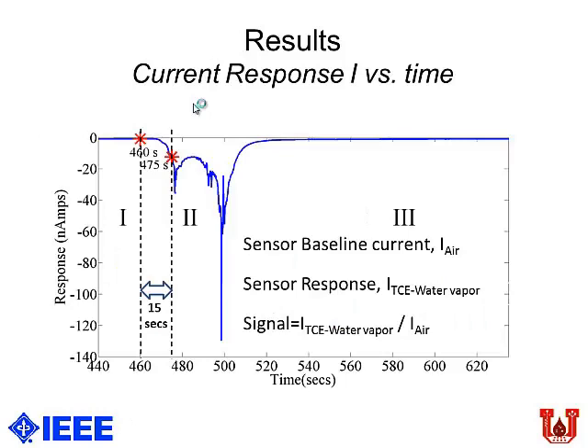So this is the actual sensor response. Your baseline, that's region 1, is when air is passed over the sensor. You don't see much significant current. And at 460 seconds, you cut the air out. Instead, you pass air through your water containing trichloroethylene, and then carry it over to your sensor. And you do that for about 15 seconds, at which you see an increase in current. And then at this point where you cut it off, your signal still increases, and within about 40 seconds you see a maximum signal. So that's your actual signal, the maximum response.